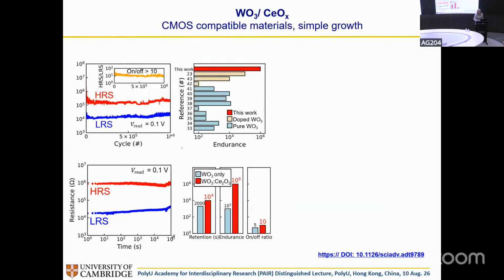And if we look at the performance of these, we can see that we have high resistance state and low resistance states, the number of cycles, that's 10 to the 6 cycles, and the resistance versus time. This is looking at the retention. Do you retain the states when you take the voltage off? The high resistance state and the low resistance state, take the voltage off, just leave the material, look at the resistance, and you see that you can go quite a good number of cycles.